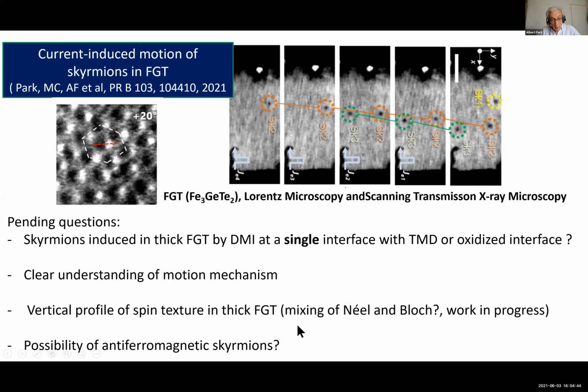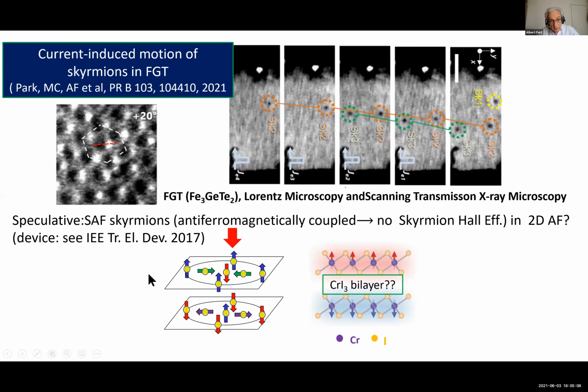Of course, if one wants anyhow to be speculative, what is the possibility, for example, of antiferromagnetic skyrmions, since we have seen that with 2D magnets there is some possibility, for example for CrI3, of antiferromagnetic coupling between two layers of CrI3. For 3D materials, in my laboratory in particular, good results have been obtained with antiferromagnetic skyrmions, skyrmions coupled antiferromagnetically, which are not subjected to the deflection in their current-induced motion. So a speculative idea that maybe could be tried is to do the same thing, but with a CrI3 layer, taking advantage of the antiferromagnetic coupling between the two single layers.